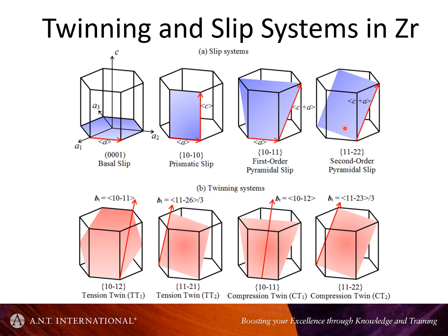The interesting thing about zirconium is even though the basal plane is the most close packed plane and is indistinguishable from the FCC 111 plane in how the atoms are packed on a single plane, that's not a twinning plane. That's simply a geometrical consequence of the ABA stacking in the hexagonals compared to ABC stacking. What that means is that a twin, which involves the shear of a partial dislocation on each successive plane in a given volume, that really is what a twin is, is not possible on the basal plane, but martensite transformations are. So you can shear every second plane in the same direction. And again, I can demonstrate that when I have my ball models.